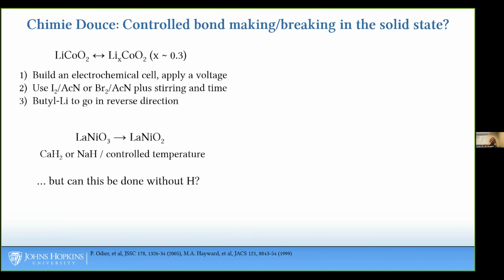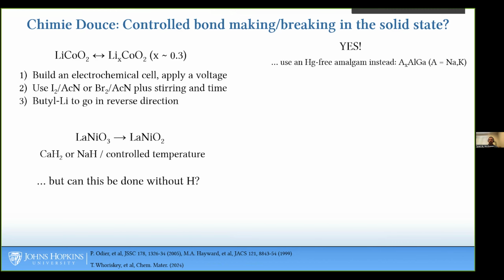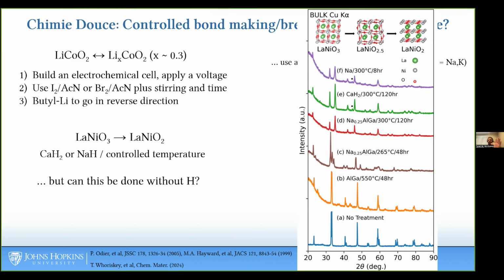Okay, but there was a lot of question in the nickelates: does hydrogen matter for the superconductivity? You'd love to be able to do this kind of reduction without any hydrogen around at all. Turns out that's shockingly hard to do, because basically almost all reducing agents contain hydrogen. But it turns out, if you think back, there's this thing called an amalgam. An amalgam is from 150 years ago, like sodium metal dissolved in mercury metal. And I don't really like my students playing with mercury, so you can come up with an aluminum gallium eutectic that serves the same purpose as the mercury, which is to say a liquid. And then you can add the alkali metal, sodium or potassium, as the reducing agent. And it works. And I guess I'm running out of time, so I think I'll just say it works.